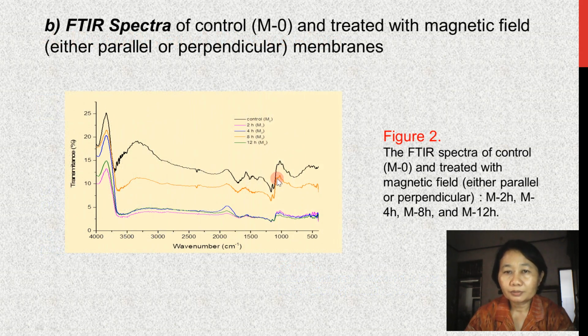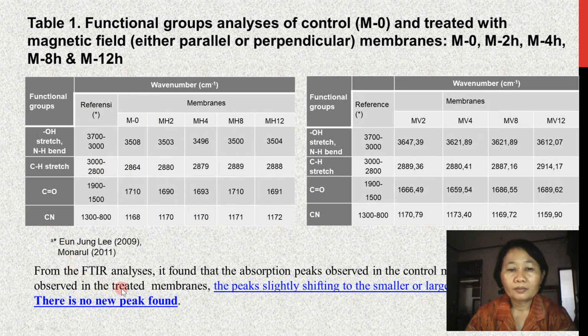For the functional group of the control and treated membranes, we also studied and reported that all the peaks found in the control membrane were also found in the treated membrane, either treated by the parallel or perpendicular magnetic field direction. Only the peaks slightly shifted to a smaller or larger wave number. There is no new peak found.